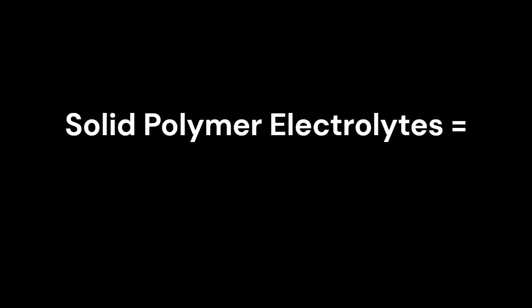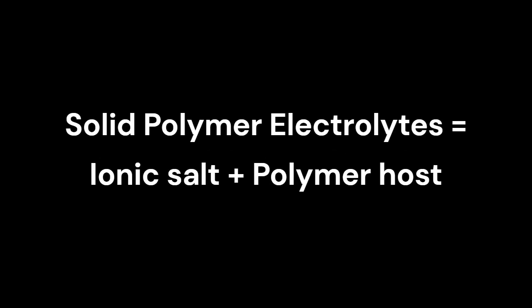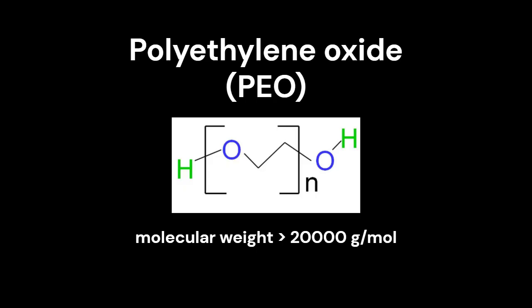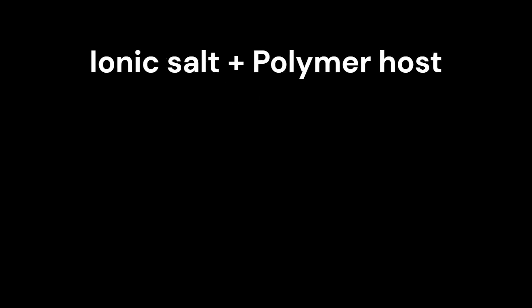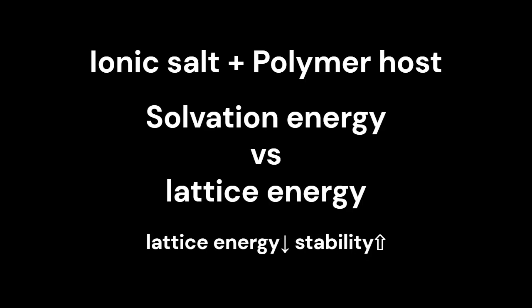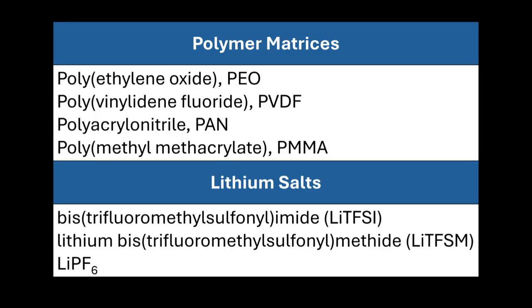Solid polymer electrolytes are formed by dissolving ionic salts in polar polymer hosts that can coordinate with the ions. Polyethylene oxide was the first polymer widely used for this purpose, although many other polymers have since been explored. The formation of polymer salt complexes depends on the balance between solvation energy and lattice energy, and stability improves when both the polymer and the salt have relatively low lattice energy. In addition, mobile anions can cause self-discharge and degrade the electrode surface, reducing device performance. Therefore, salts with large organic anions, such as LiTFSI and LiTFSM, are often preferred.